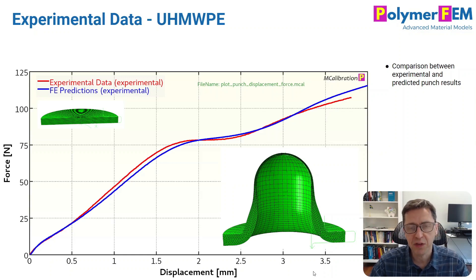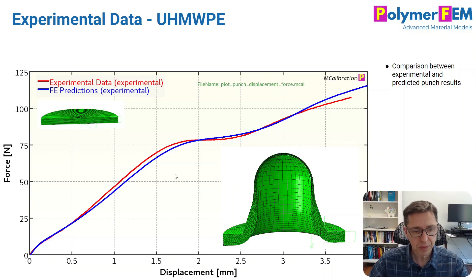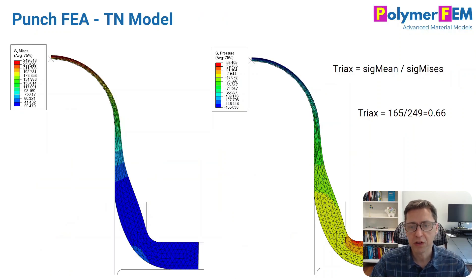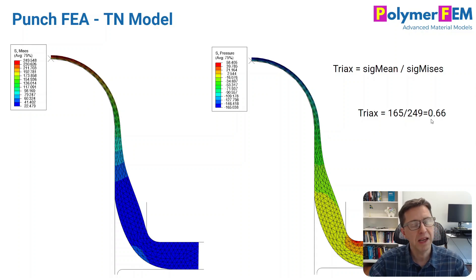The nice feature of this experiment is that it's close to a biaxial test and it's relatively easy to perform. So I have data for when this polyethylene fails in biaxial loading. I was able to simulate that and come up with a failure stress and strain in biaxial loading from these experiments. Here are some screenshots of the simulations of this biaxial punch test. I calculated the triaxiality — I get approximately 0.66 — indicating that indeed it's close to a biaxial test.